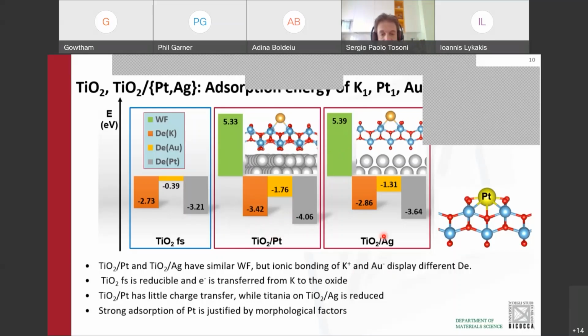on silver. And this is due to the interplay between the film and the substrate. Titania on platinum has a small charge transfer, while in the case of silver, the titanium dioxide film, even in absence of any adsorbate, is negatively charged. There is some charge spillover from silver to titania. And this in turn influences a lot the formation of ionic adsorbates on the film.